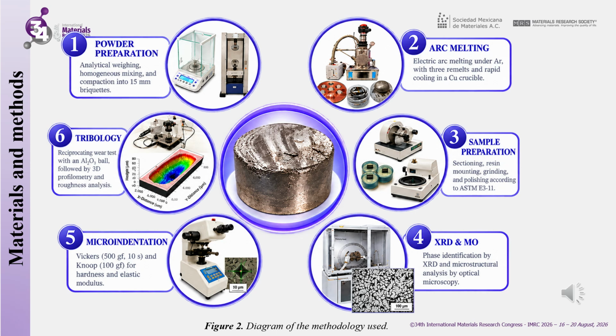Structural and microstructural characterization was conducted utilizing X-ray diffraction and optical microscopy, respectively, employing standard procedures for the identification of crystalline phases and microstructural analysis. For the Vickers microhardness test, a load of 500 grams force was applied for 10 seconds, and the diagonals of the indentations were measured using an optical microscope to calculate the hardness in accordance with ASTM E92. For the Knoop microhardness test, a load of 100 grams force was applied, and the anisotropy of the material in different directions was assessed in accordance with ASTM E384.